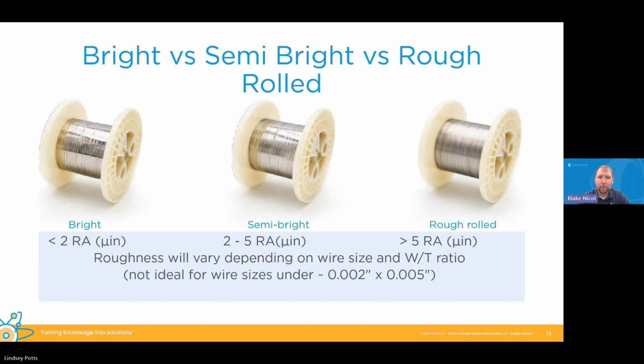Roughnesses will vary depending on the wire size and our width to thickness ratio, meaning our width divided by our thickness. So it will vary depending on what size we're working on. We did find that this is not really ideal for sizes under 2 thou by 5 thou, where we start seeing that the texture of semi-bright and rough rolled overpowers the size of the wire. The grain is just a little bit too large on those products.